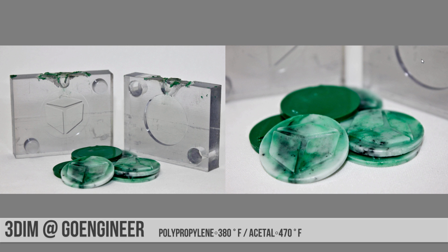This was the first mold I created. It's a Vero clear mold, and it's just a little button with our logo on it. You can see the top portion of the mold is damaged. I shot probably 30 different parts out of this, and I was becoming very aggressive with how much pressure I put on the mold and how long I packed on the mold. And because we had a very hot brass nozzle touching the tops of our parts, the brass nozzle in this case is set to 380 on the low end or 470 on the high end for these materials. I have a 470 degree brass nozzle putting pressure on the top of my part for 20 seconds. That's eventually when it failed.